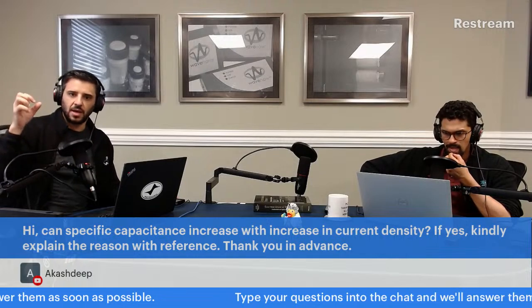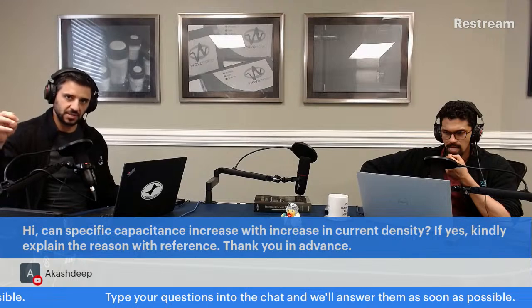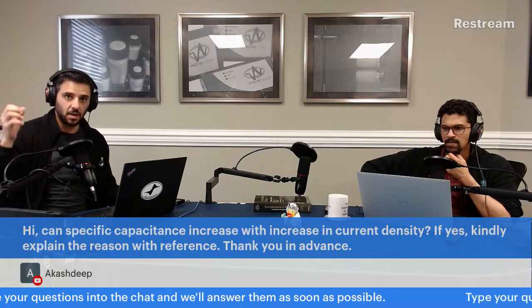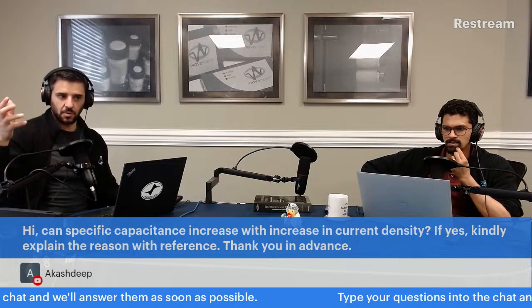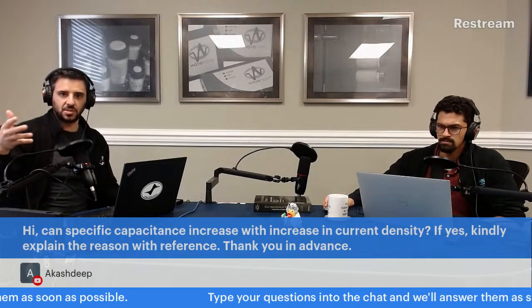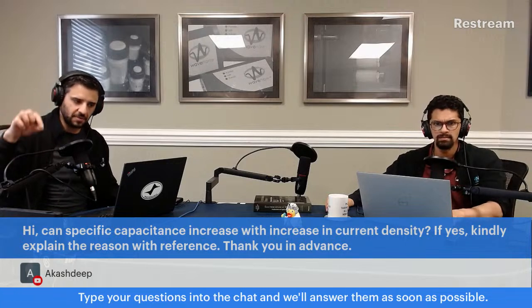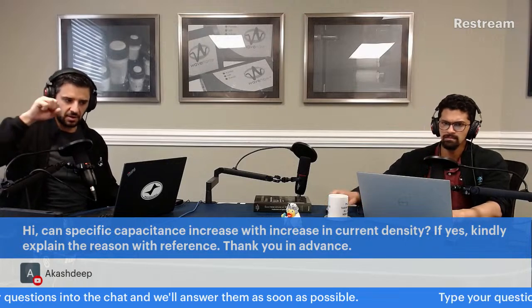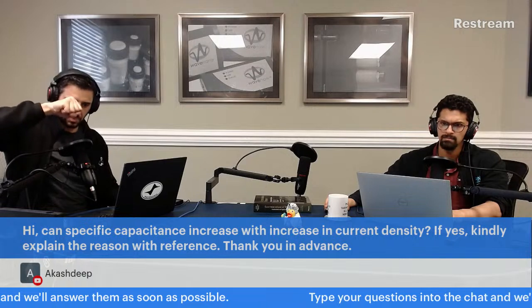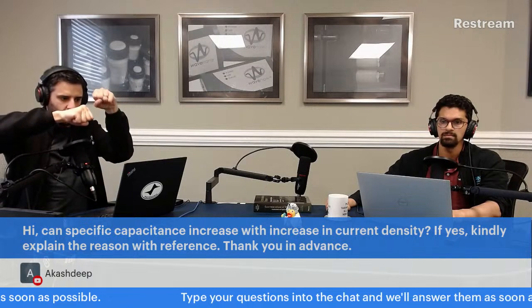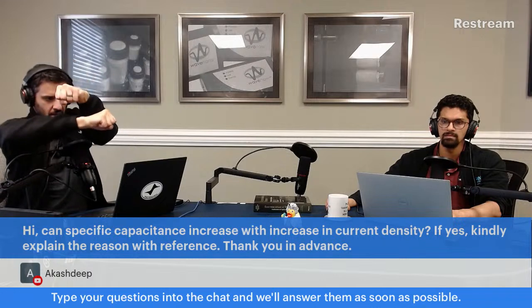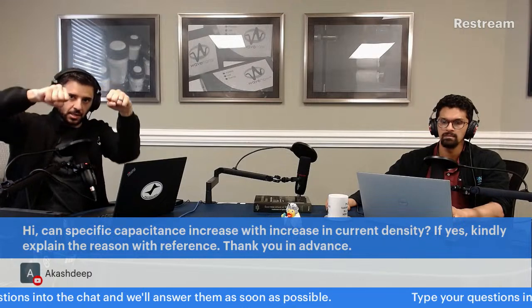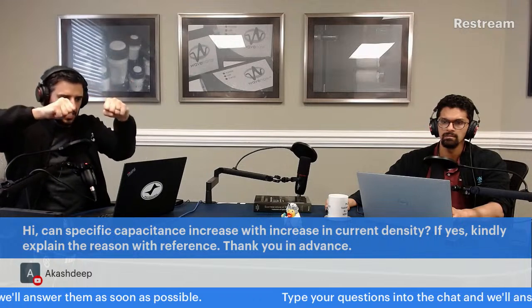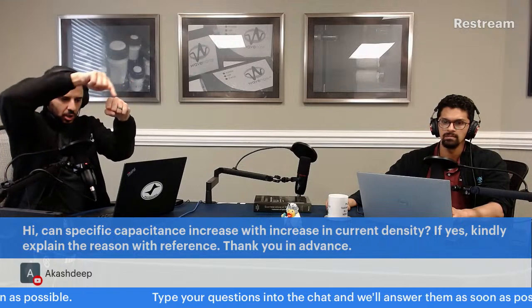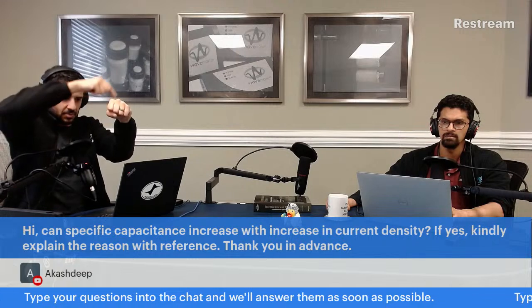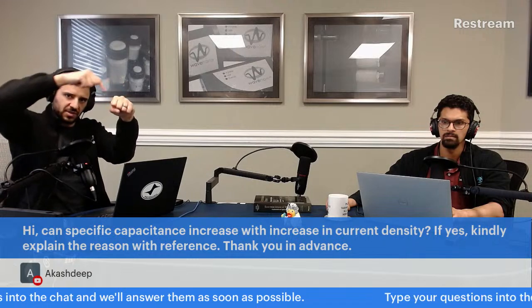So if you have nanoparticles of platinum, for instance, this is a phenomenon that is observed regularly. If you have nanoparticles of platinum, the best way to access them is to use a very small amount of mass because they're very small. You can think of them as very small orbs or balls. And if you have one here and one here and one here, they're sitting on a substrate of carbon or something like that. And all around this orb of platinum, all around it is accessible. It's got a huge amount of surface area, right?